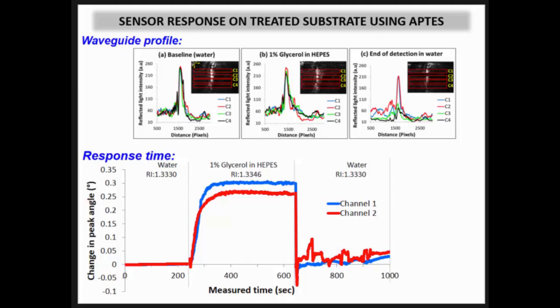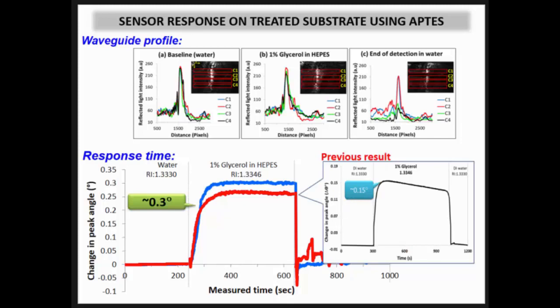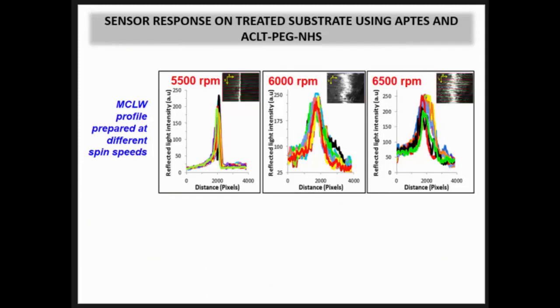So meaning that it has not fully covered the surface using APTES, and maybe that's because only some of the binding, like electrostatic charge, just happens on the substrates without any strong binding. However, in terms of response time, if you can see here, we compared this result with the previous one that we optimized before. We do have some improvement in terms of sensitivity. Yes, it's good. However, the homogeneity of the layer is still not certified.